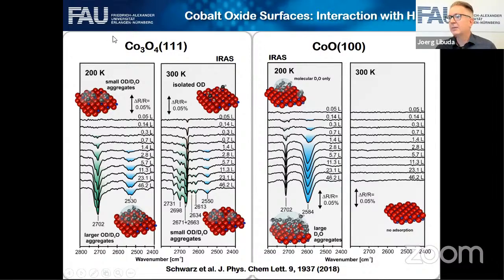And remember, both surfaces are terminated by cobalt 2+ ions and oxygen 2- ions. The only thing that is different at the surface is the coordination environment of the ions. Well, of course, there's also a different oxidation state for the cobalt, but at the surface, this is the difference: the very structure of the surface, the coordination environment of the ions. Now let's look at the interaction of water.